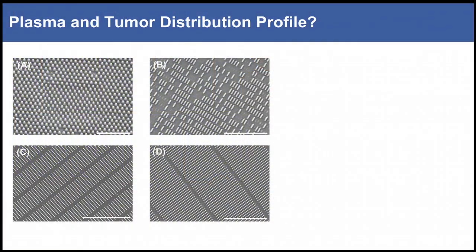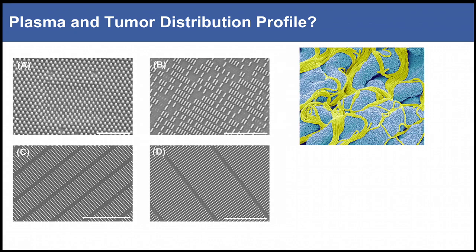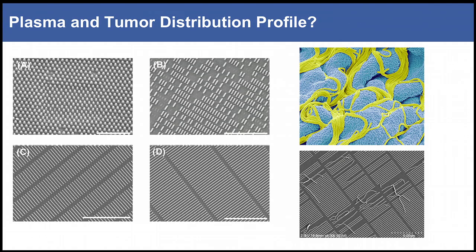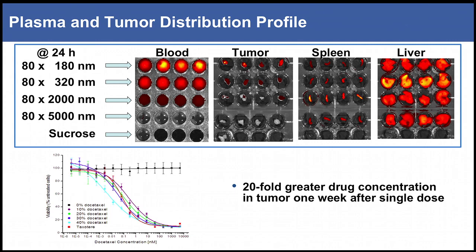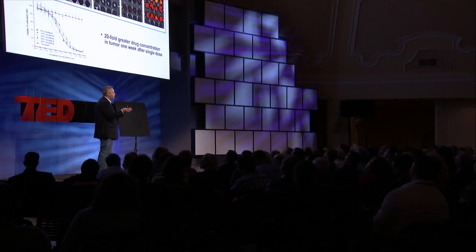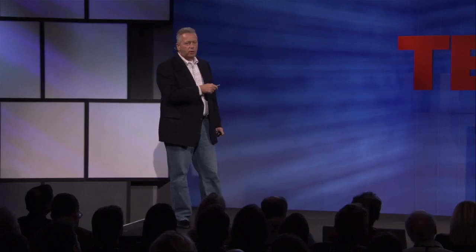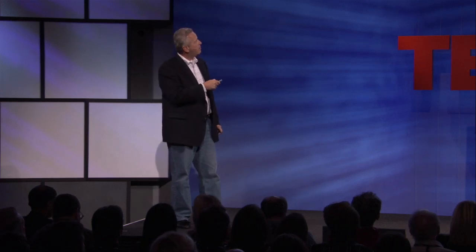We're extending this to other sizes and shapes by matching mechanics. These particles are 80 nanometers in diameter — remember, a red blood cell is 8,000 nanometers. We can begin mimicking blood-borne bacteria, which are often very elastic and very rod-like. We use these as ways to enhance deposition profiles — varying size and shape, injecting them in animals, and looking at where they go in different organs. Patterns emerge, and we use sizes and shapes as a passive characteristic to facilitate desired deposition profiles. We can load these with chemotherapy agents and achieve 20 times more drug deposited in the tumor compared to the standard of care.